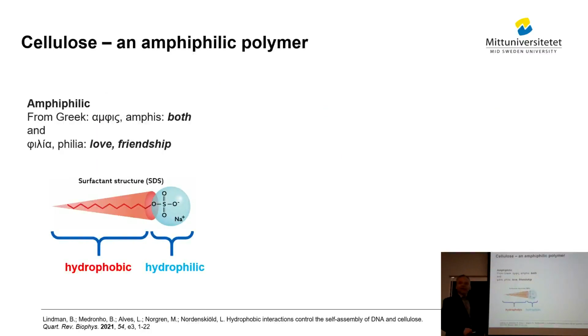So, as mentioned, cellulose is an amphiphilic polymer. That is one of the things that we have picked up and worked on a lot and tried to show more about. We've been working with emulsions, for instance, which is a good study case to see how cellulose in solution might actually go to different surfaces or interfaces between oil and water. Orlando was actually opponent to one of our PhD students, Carolina Costa, just some year ago, when she presented her thesis. And with surfactants, it's very outspoken: you have the hydrophobic tail and the hydrophilic head group, and in this case, the normal SDS is a representative of that.